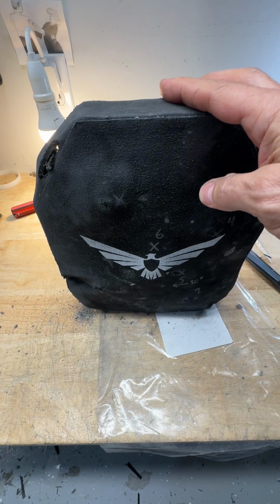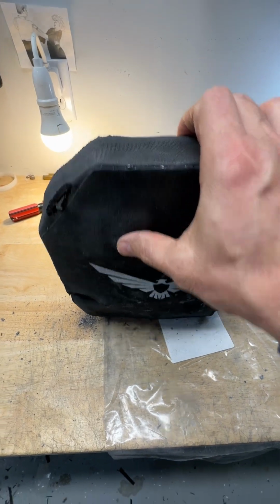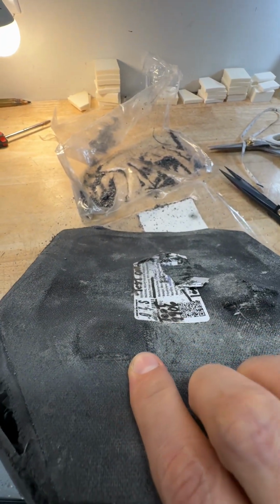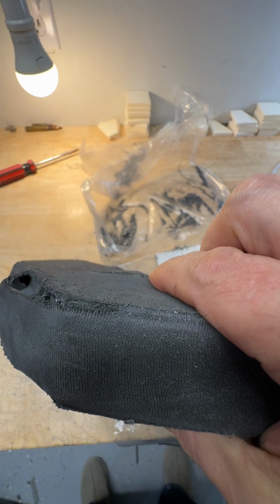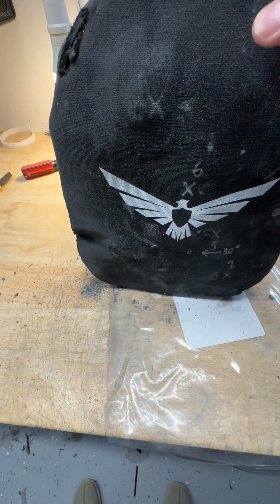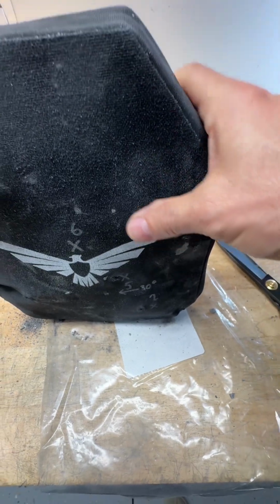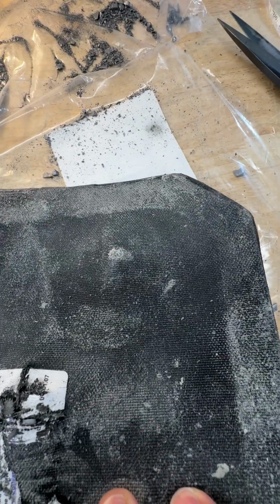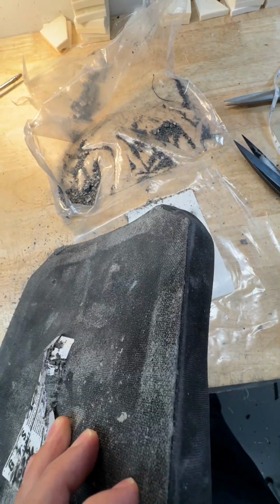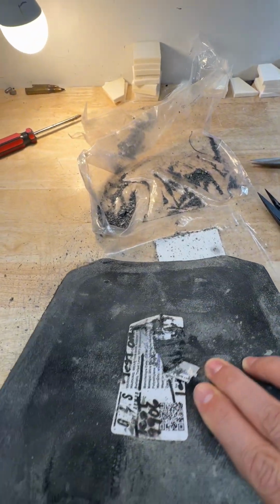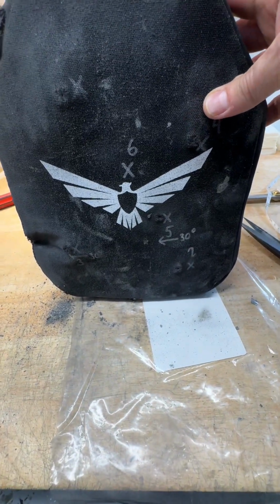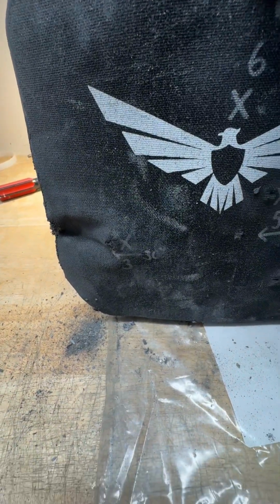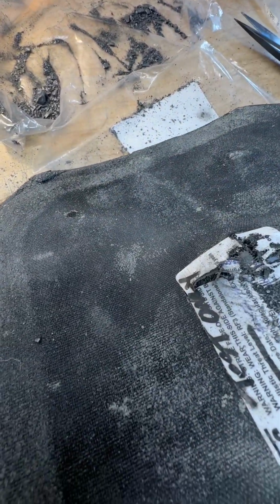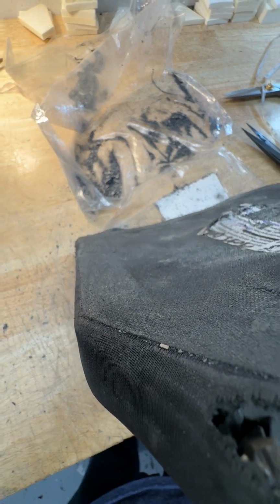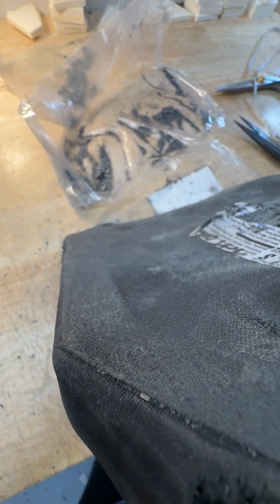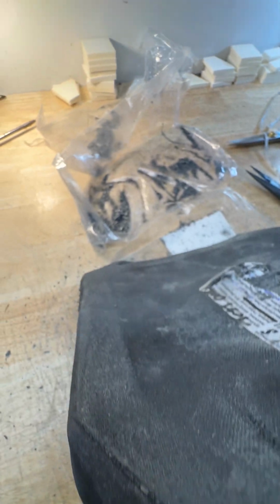Looking at the plate, we had a very good result. We had shot 1 here. That's the resultant BFD. Very little obvious back face deformation. And then we had shot 2 right here, kind of in the lower right-hand corner. And that was the back face deformation there. Very little BFD. Then we had shot 3, which is kind of over in this corner here. And you can't even see the back face deformation in the plate itself. You can see it in the energy in the test report.